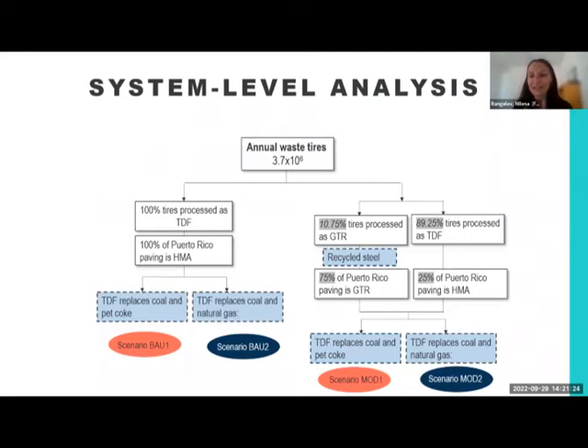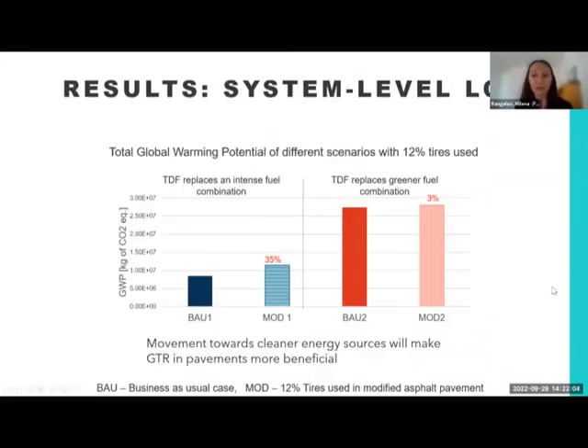We have done extensive analysis on how much that could be. And we have discovered that if you stretch all Puerto Rico systems, you can only eat up around 11% of tires. Keep in mind, this is extremely optimistic scenario. However, if we do that, we can achieve 75% of Puerto Rico paving with GTR, which is what policy was investigating, and 25% of paving will remain HMA. So in that case, we would also have some tire-derived fuel because pavements cannot eat up the entirety of tires that are available. There are just too many.